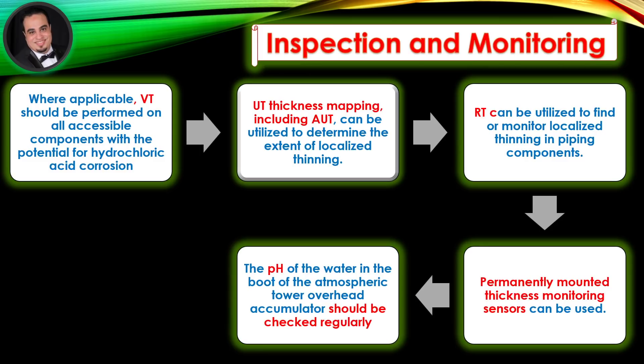Inspection and monitoring: where applicable, visual testing should be performed on all accessible components with the potential for hydrochloric acid corrosion. Ultrasonic testing thickness mapping, including automated ultrasonic testing, can be utilized to determine the extent of localized thinning. Radiographic testing can be utilized to find or monitor localized thinning in piping components. Permanently mounted thickness monitoring sensors can be used. The pH of the water in the boot of the atmospheric tower overhead accumulator should be checked regularly.